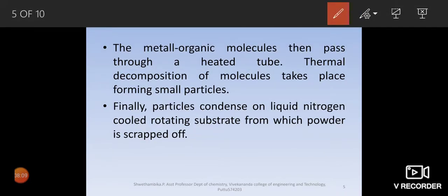In the fourth step, these metalorganic molecules then pass through a heated tube. The heated tube is nothing but the hot zone of the furnace. Then, what happens here? Thermal decomposition of the molecule would take place forming nanoparticles or smaller particles. Then, the next step, the particles would condense on liquid nitrogen cooled, this must be remembered, liquid nitrogen cooled rotating substrate or cold finger from which the powder could be scraped off.